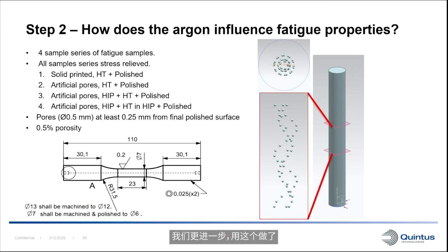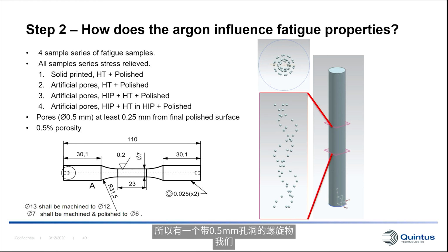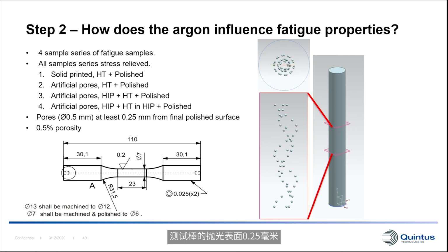We then took this a step further and made the tensile bars out of this for analyzing the fatigue properties. And so there was a spiral or a helix printed with 0.5 millimeter pores. And we ensured that they were at least 0.25 millimeters from the finished polished surface for the test bars. And these were then tensile fatigue tested with R 0.1.